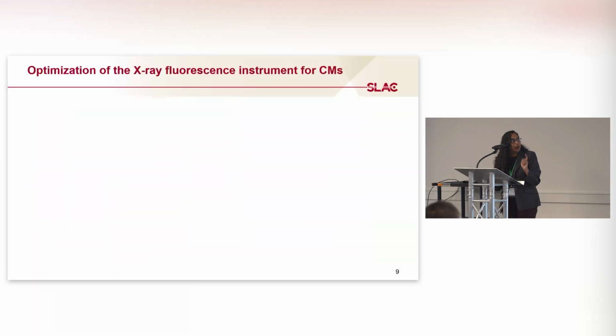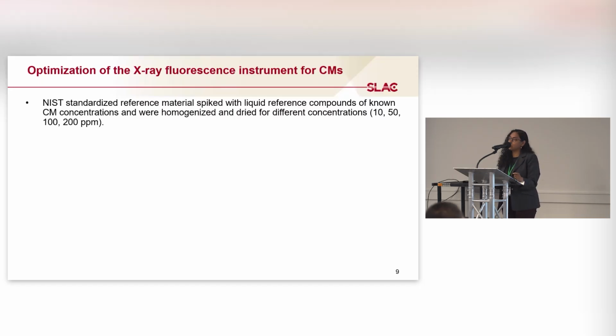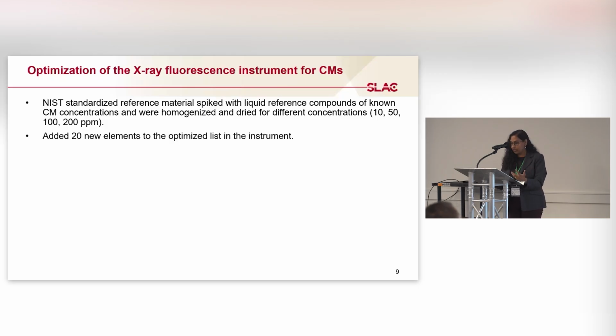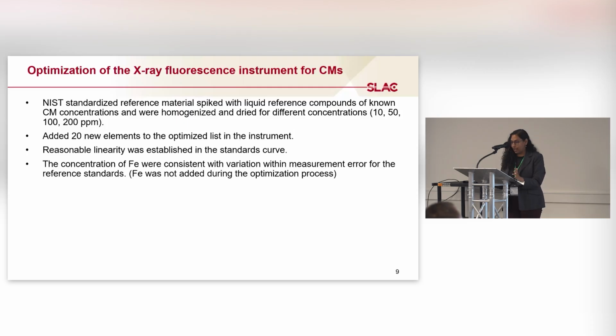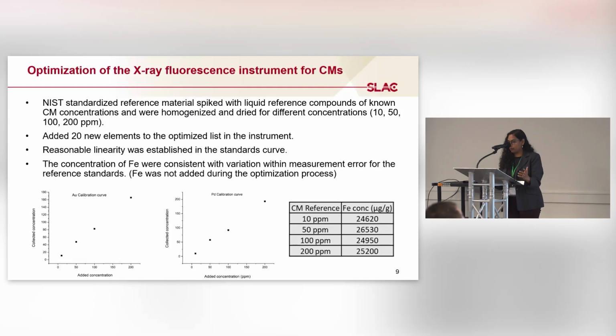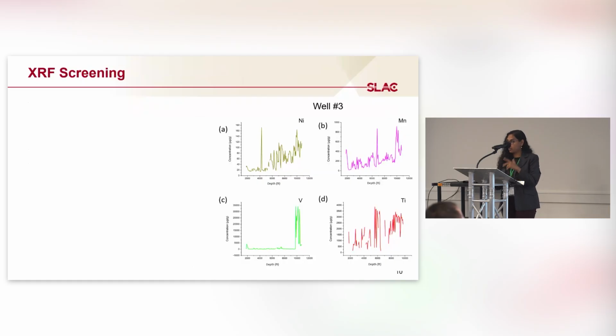So first, when I was trying to do X-ray fluorescence measurements on these samples, the X-ray fluorescence instrument was not optimized for these many critical minerals. So first, I had to optimize the instrument by taking NIST standard reference material and spiking those with different concentrations of the different solutions. And 20 new elements were added to the list. And after that, I will go to the results of this analysis.